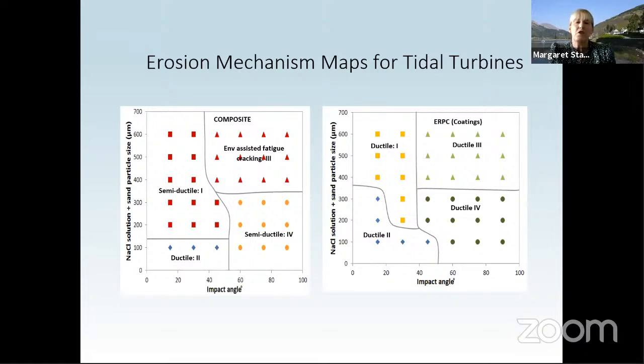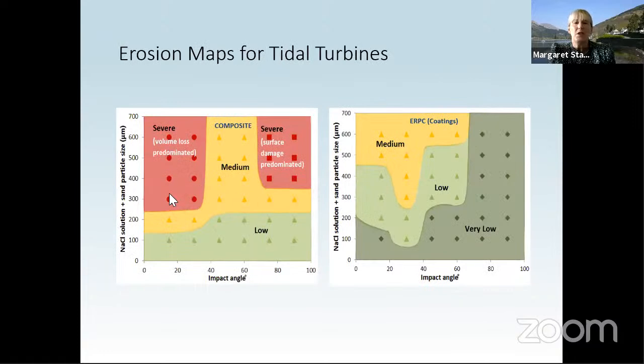So these are the kinds of maps that we can generate for these kinds of conditions, coated and uncoated. And this is a wastage map here showing that obviously uncoated results in much greater wear than coated. Now, for the tidal turbine materials that have been developed to date, and those that have been used on turbines deployed and tested at sea, what they've been finding is this kind of regime. There has been catastrophic failure of these turbines. So obviously they need something like this.